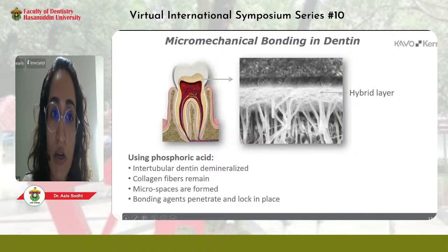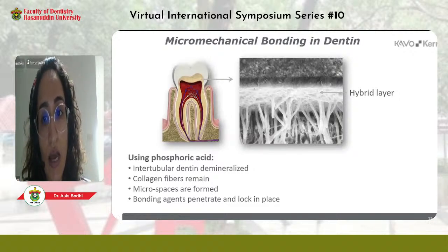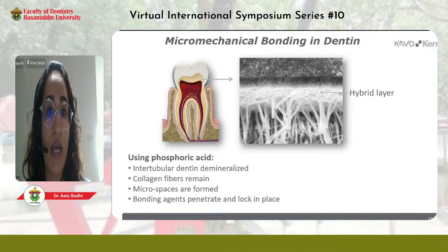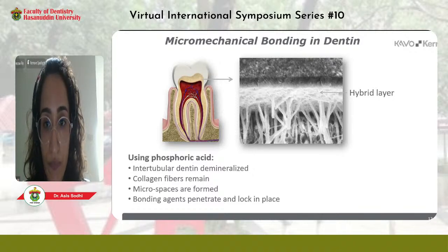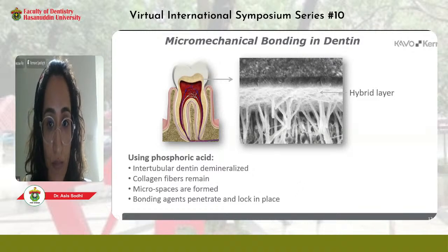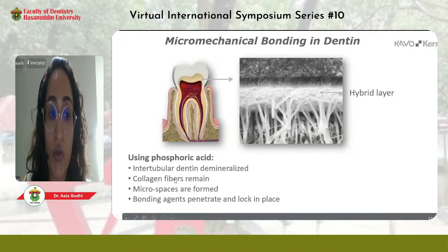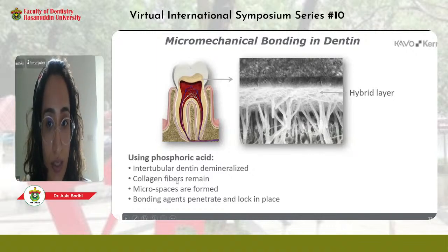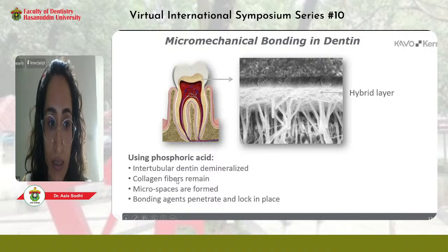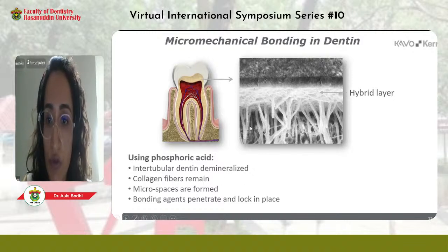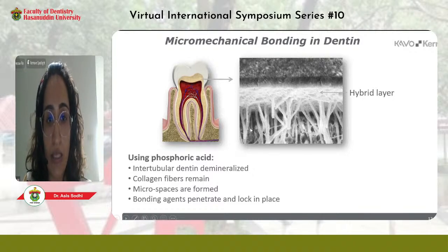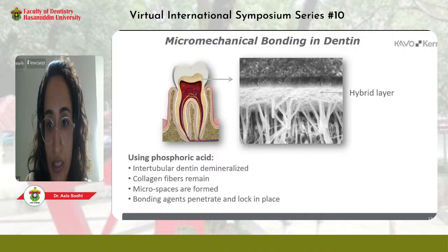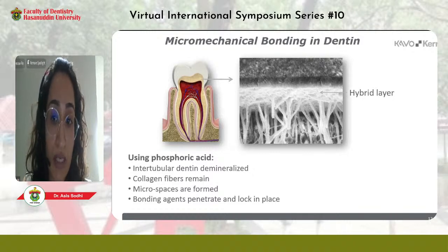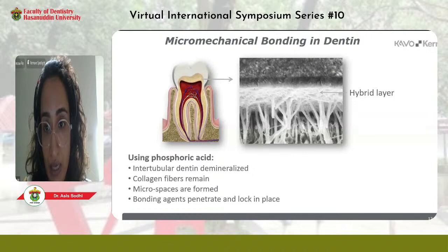So we saw how micromechanical bonding looks like on the enamel surface. Let's look at how micromechanical bonding looks like in the dentine surface. So if you see the image here, it's pretty different from what we were looking at in the enamel section. So what we are doing here is that you're using phosphoric acid as a part of the total etch process. When you use phosphoric acid, there is intertubular dentine that is demineralized. Okay, as a part of the demineralization, the intertubular dentine is removed, and so there are spaces formed. However, the collagen fibers that are there inside the dentine, they still remain in place.